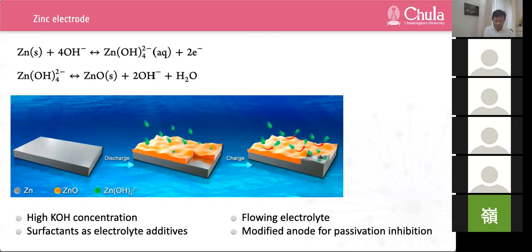Well, among these methods, using a high concentration of alkaline electrolyte, in this case we use KOH, to increase the solubility of accumulated zinc oxide is the simplest method, because the passivation layer is loose and unstable under high pH conditions. But this method also causes serious anodic corrosion because we use high concentration of KOH, right? So it's kind of a trade-off between corrosion and passivation. The other method is we can use additive. We add additive to electrolyte.